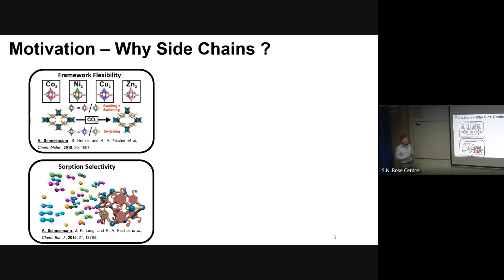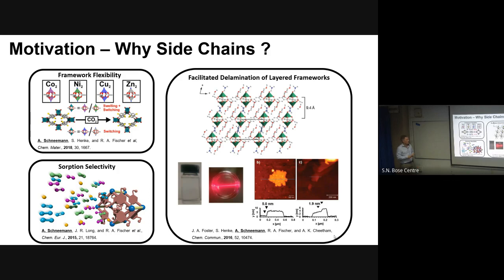And the third thing that we discovered was if you have a layered metal organic framework with side chains attached, this makes it very easy to exfoliate the frameworks upon sonication when they are dispersed in solution. For these copper paddlewheel frameworks with functionalities, you get sheets as small as 1 to 2 nanometer layers upon attachment of these side chains.